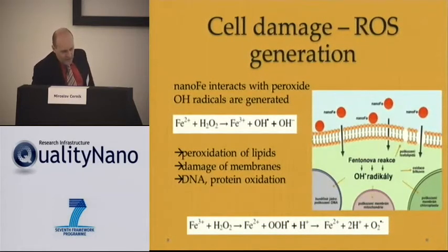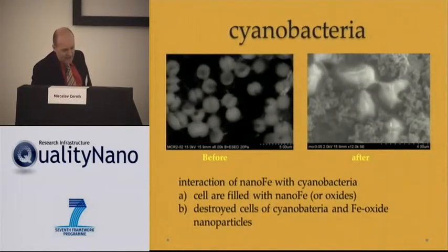This is due to the interaction of the iron with peroxide, and it produces OH radicals, which are dangerous, of course, for the cell. We did some study where we applied the iron to cyanobacteria, where of course the negative effect is sort of good, because we want to destroy the cyanobacteria. The picture on the left is just after the application, where the nano iron is sort of captured by the bacteria, and this picture is after some time, where the cells are totally destroyed, and you see the residue of the cells and the iron oxide outside, so we are able to kill this cyanobacteria, which is good for